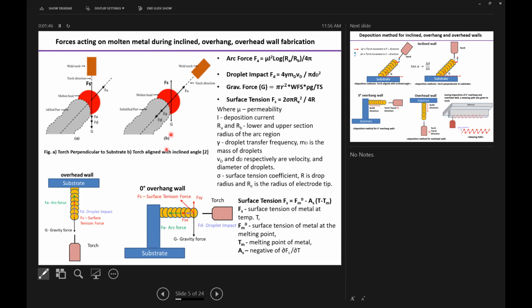My main focus is to manufacture the overhead and overhang structures using CMT based wire arc additive manufacturing. In CMT based wire arc additive manufacturing, the cold metal transfer technology is used. This slide shows the various forces acting during the deposition of an inclined wall. The major forces are the arc force, droplet impact, gravitational force, and the surface tension force. The arc force mainly depends upon the current during the deposition process. The droplet impact depends upon the mass and the velocity of the material.